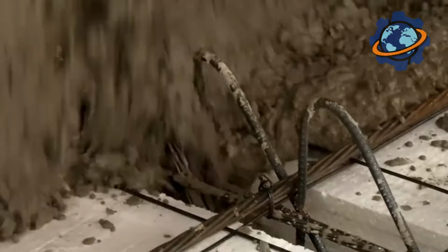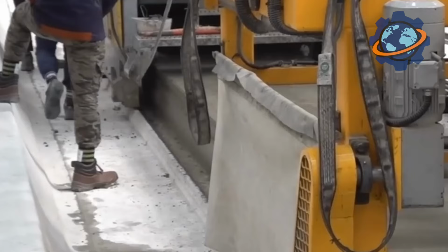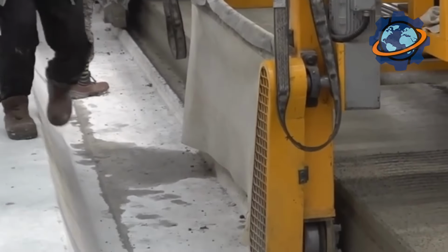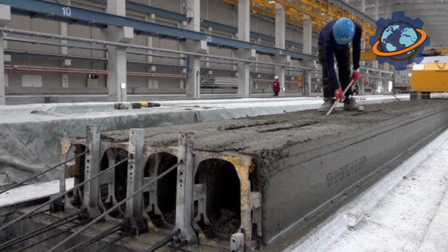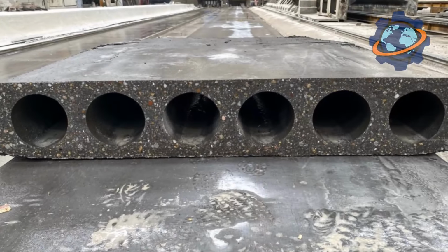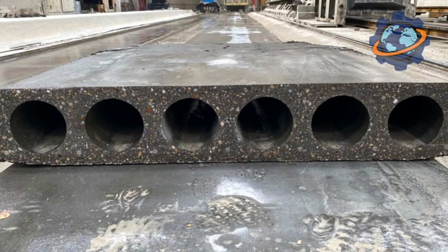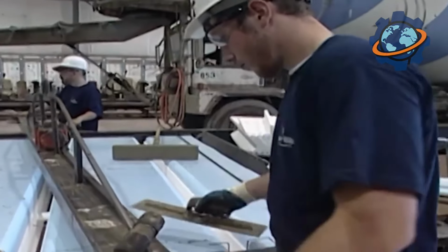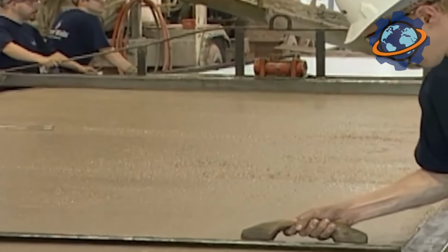This isn't just building, it's a conveyor belt running at a speed unthinkable for traditional pour-on-site concrete. And now for the main trick, the hollow cores. These holes inside aren't just for looks. They slash the slab's weight by almost 50% compared to a solid slab of the same thickness and strength.